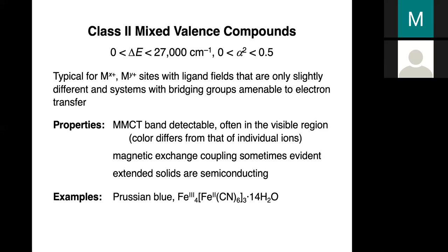First example will be a really old compound known as Prussian blue. The formula you can see here, it's a cyanide bridged compound. We'll look at the structure in a minute, but it has iron 2 and iron 3. So you can see there's a 4:3 ratio of iron 3 centers to iron 2 centers. And then there's a lot of water in this structure as well. It's a very old compound. It's been known for more than 300 years. And it's a very simple reaction to make this compound, but it's very striking when you produce it.